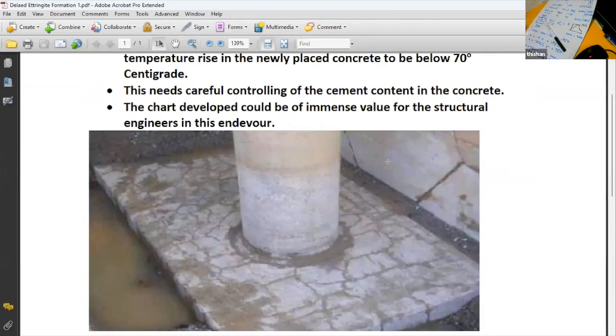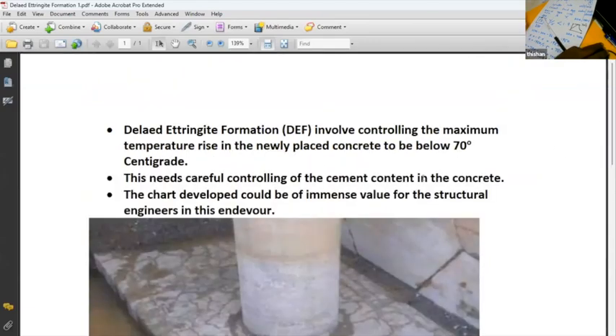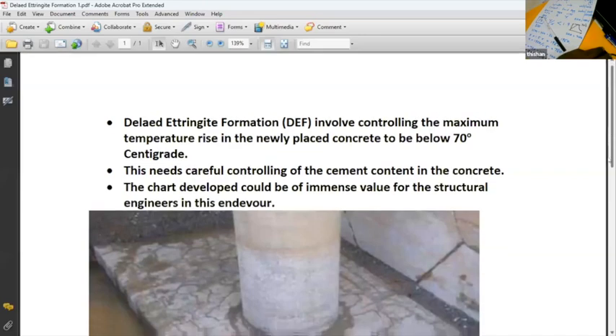Okay? Not everything. So the important thing is you must control the temperature. Delayed ettringite formation involves controlling the maximum temperature rise to newly placed concrete to be below 70 degrees. This needs careful controlling of the cement contained in concrete. The charts developed could be of immense value for structural engineering in this endeavor.